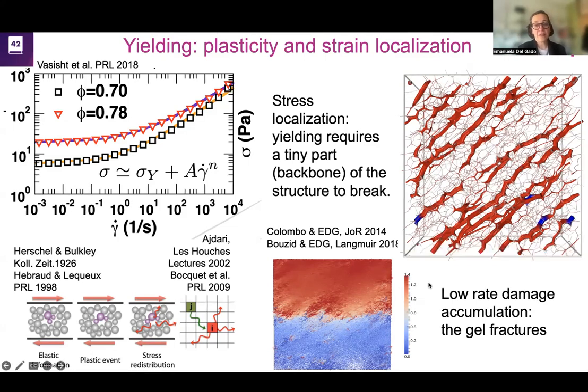And so, for example, as you go very slow, you can in fact favor the fracturing of the system. This is what we see in these simulations: when you are deforming the gel slower, you are promoting the densification of the gel in some part of the structure, which then triggers the formation of further connections as I keep shearing, until I make some part of the gel stiffer and stiffer, and some part less and less connected, until I'm able to break, and I produce a fracture plane through my gel that you can see here. So this type of dynamics is what we can see happening microscopically, and what should be in our head when we try to understand what's happening in the rheological response that we measure macroscopically.